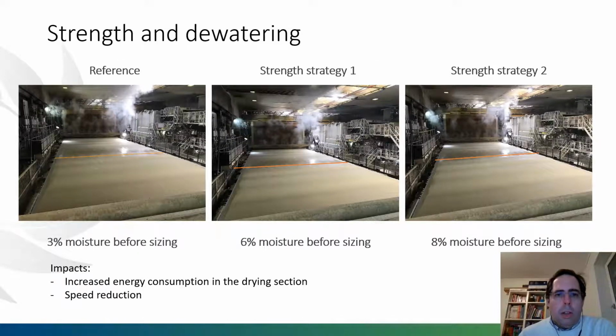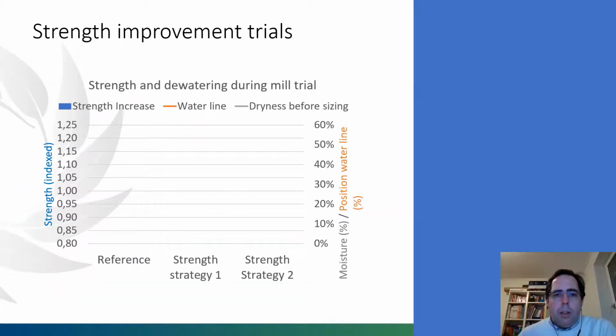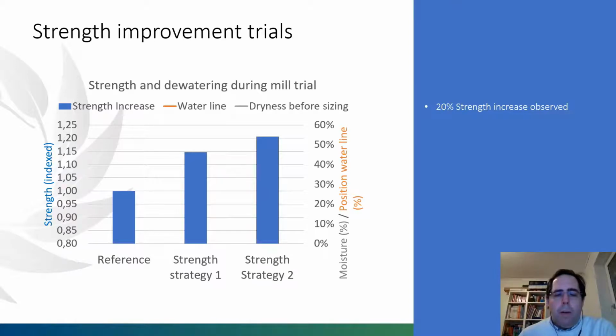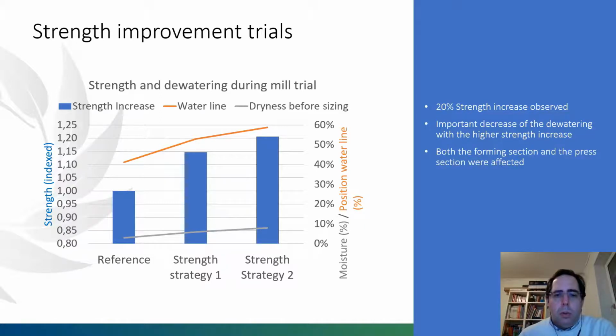What we see now in the screen is what happens many times when a mill starts to increase the strength. What we will see many times is a reduction in the dewatering, as we could see in the water line on the wire, and a higher difficulty to remove this water afterwards in the press. In this case, if we see this graph, we will see that despite a potential increase of up to 20% of the strength, the water line was moved towards the end by more than 20%, and also the dryness before the size press was also reduced.